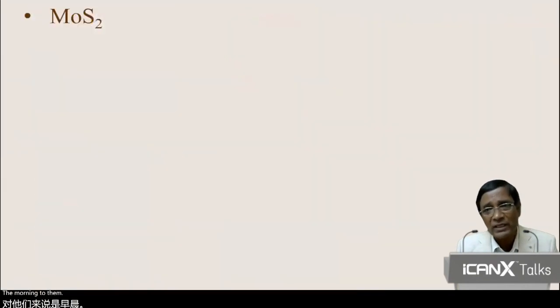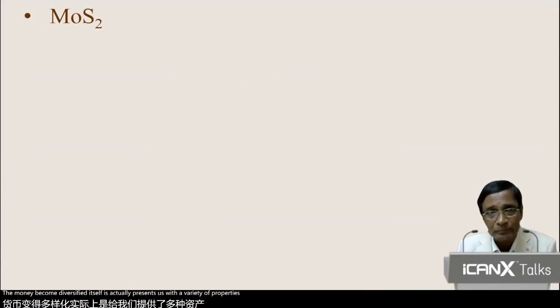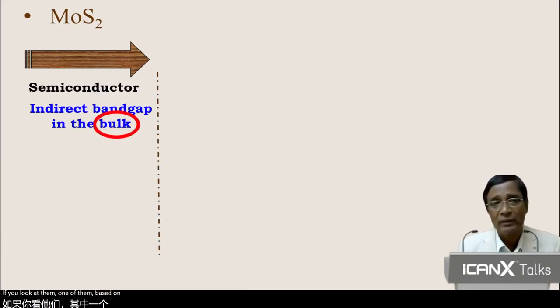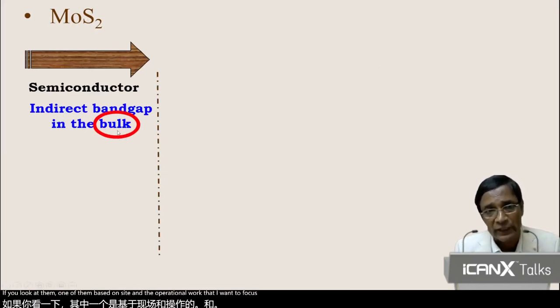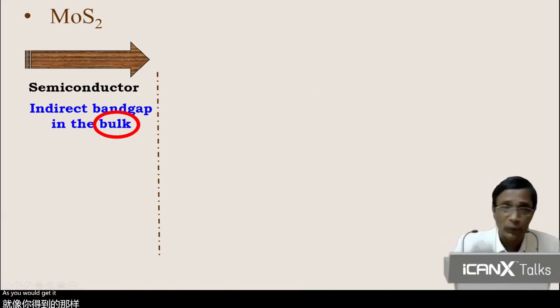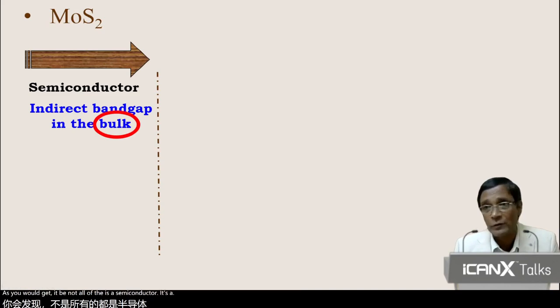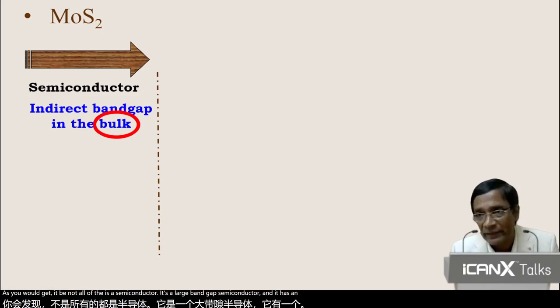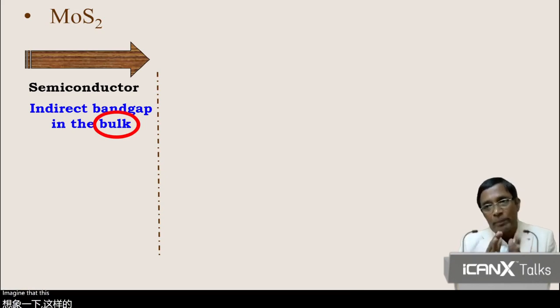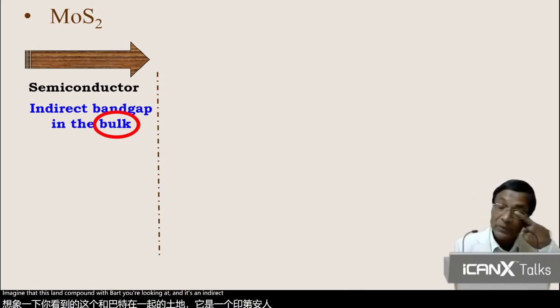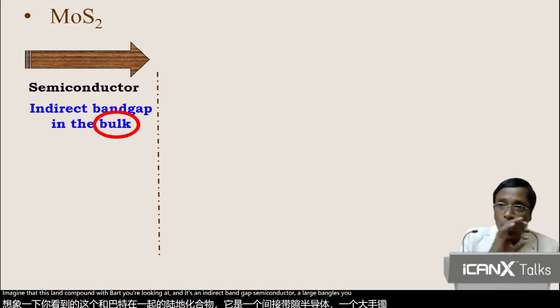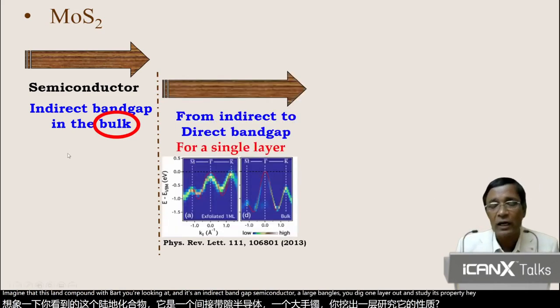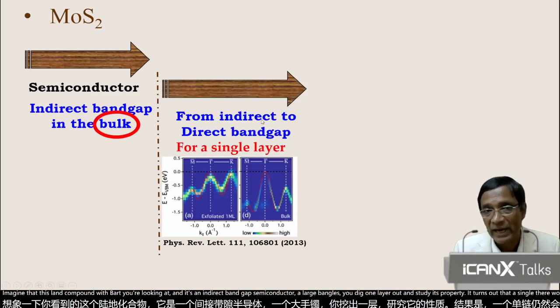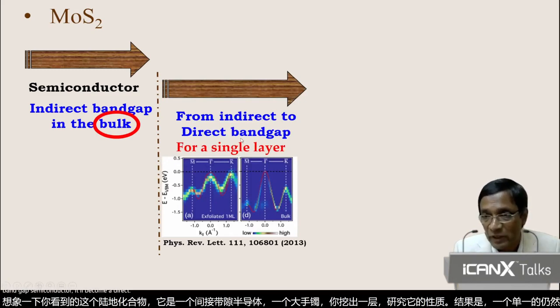Molybdenum disulfide itself presents us with a variety of properties. The operational word that I want to focus on is the bulk, as you will get a piece of molybdenum disulfide. It's a semiconductor. It's a large band gap semiconductor, and it has an indirect band gap. Imagine this layered compound whose bulk you're looking at is an indirect band gap semiconductor with a large band gap. You take one layer out and study its property. It turns out that a single layer would still have a large band gap, but instead of being an indirect band gap semiconductor, it will become a direct band gap semiconductor.